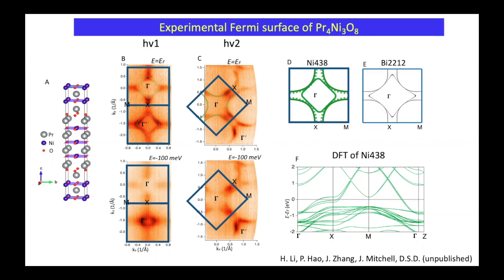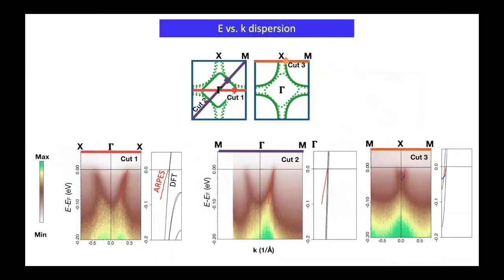I can go into more detail and show you the E versus k. This is not yet published. So cut 1 is along here. Cut 2 would be like your nodal cut. And then cut 3 would be like antinodal. So here's the raw data. These red lines are fits to the peak position through the data. These are just MDCs for now. That dispersion is shown here, experimental dispersion, and I overlay that with the DFT. So you can see kF matches extremely well, like you'd expect in your Fermi liquid type thing, your volume from surface volume, but the masses are heavier in the experimental data. And that's sort of what we are used to from cuprates.